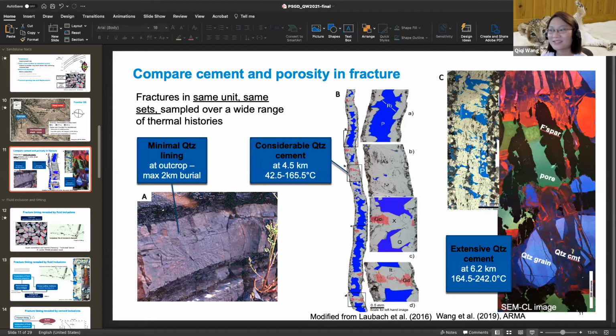That's a great question. So I would say there are cases where we think the fractures contribute more to permeability than to porosity, because from my experience with subsurface data sets, the fracture porosity is usually less than 1% of total porosity. So you can count it, but it contributes more to permeability, I would say.